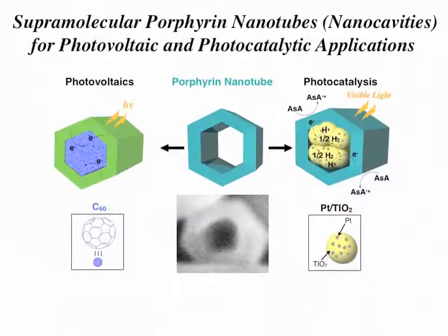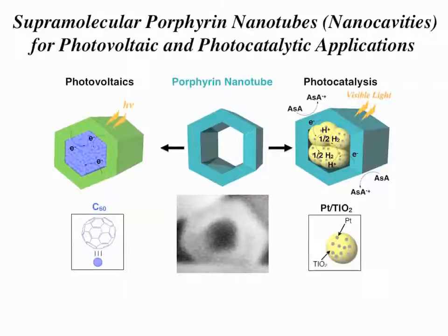We have also prepared supramolecular porphyrin nanotubes for photovoltaic and photocatalytic applications. Fullerene or platinum-deposited TiO2 nanoparticles were successfully encapsulated within porphyrin nanotubes. In both cases, large enhancements of solar energy conversion properties were observed.